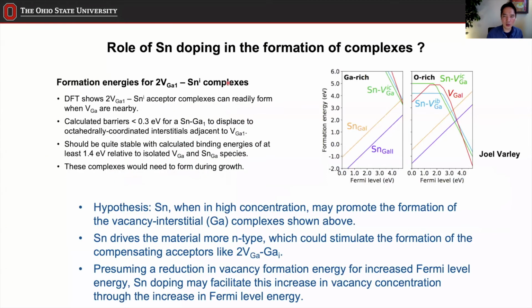But the more difficult question to answer is what the tin doping does to the concentration of these defect complexes that we observed. Do we have a large number of complexes because the tin goes into the cation site, or is it something else? That's something that we were discussing with our theory collaborators. The hypothesis that we came up with is that when we have tin in high concentration, they may promote the formation of vacancy interstitial complexes in a certain way. And that way is like this.